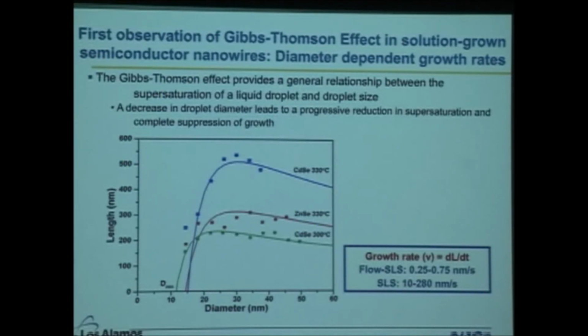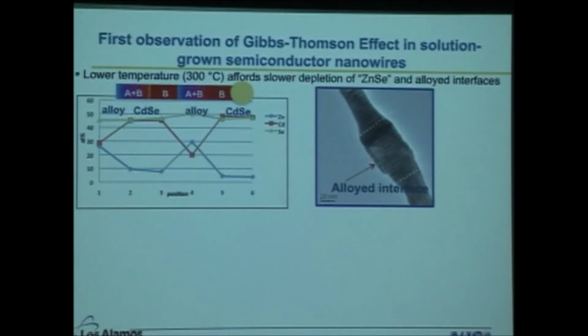And so the other thing to point out here is that the flow SLS growth rates that we calculate are very, very small compared to traditional SLS. So less than a nanometer per second, versus tens to hundreds of nanometers per second. And so we've achieved what we wanted to do in terms of more controlled growth, and we've obtained a new ability to look at kinetics in the SLS system. And so that was all good.